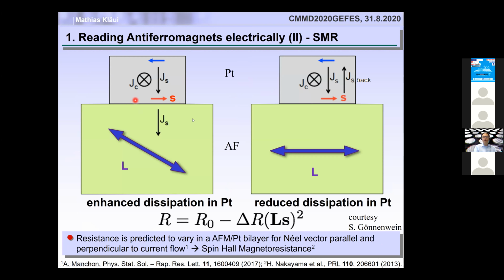And essentially, if you put on top of an antiferromagnet a layer of a heavy metal like platinum, where due to the spin-Hall effect, you generate a spin accumulation at the interface, then this spin accumulation interacts with the Néel vector depending on the direction of the Néel vector with respect to the spin accumulation. And so what you can measure is the resistance of the platinum, and this will be different whether the Néel vector has a component perpendicular to the spin accumulation or whether the Néel vector is fully parallel to the spin accumulation. And so this should fundamentally allow us to detect the orientation of the Néel vector.